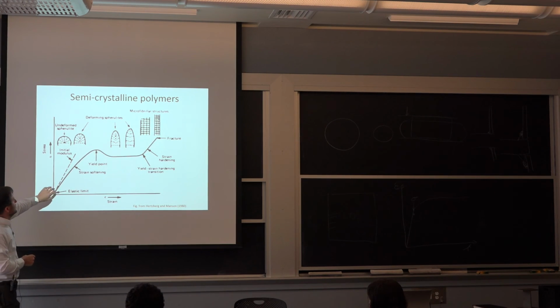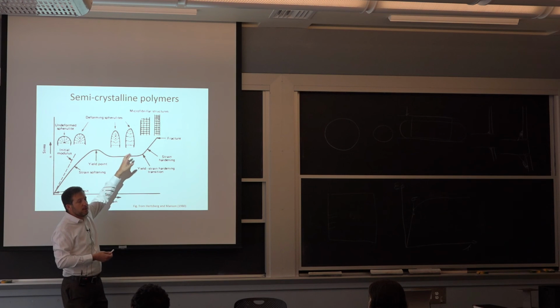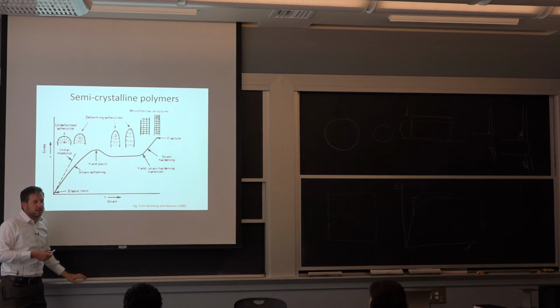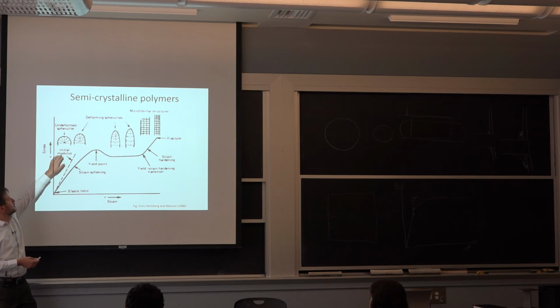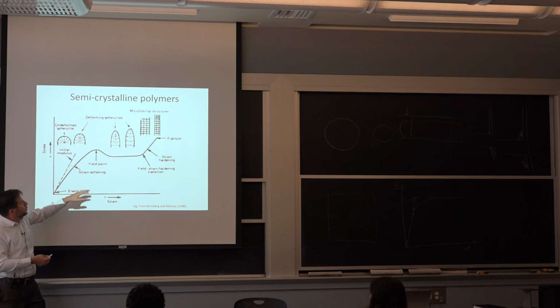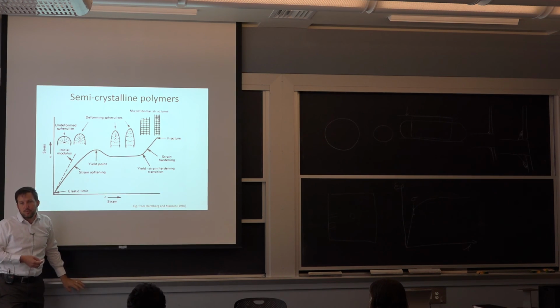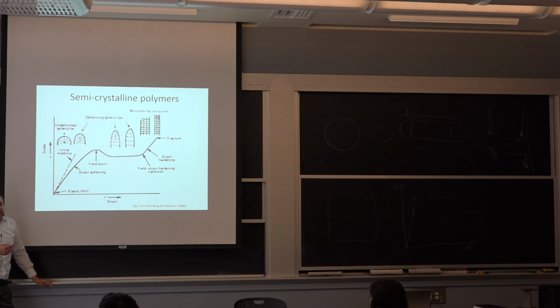This is probably a good starting point when we're going to talk more details about forming. So if we cast the polymer and got these spherulites that we've talked about two or three lectures ago, and now we start deforming them, they'll break down and the crystals orient themselves in the direction of pulling. So now all of a sudden you transition from having mostly the amorphous zone inside the spherulite stretching to essentially having all the crystallites lined up to make a cord. So if you have a nylon cord or a polyethylene cord, you're looking at a strength that is about 5 times what you got out of molding, because now everything is well oriented and everything is also more resistant to creep.